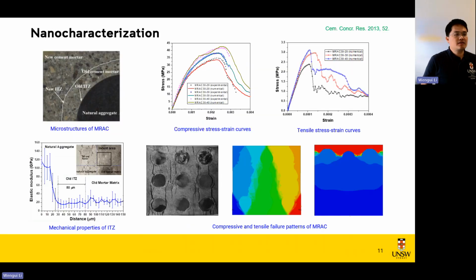So here, when we conduct many nanoindentations on random regions in, of course, the interfacial transition zones, ITZs, in recycled concrete, then we can obtain the thickness of the ITZ and the relative strength between the ITZs and cement matrix by statistical analysis. And then we use these parameters for numerical simulation. So here you can see the numerical results are in good agreement with the experimental results in terms of the stress-strain curves and the crack patterns.